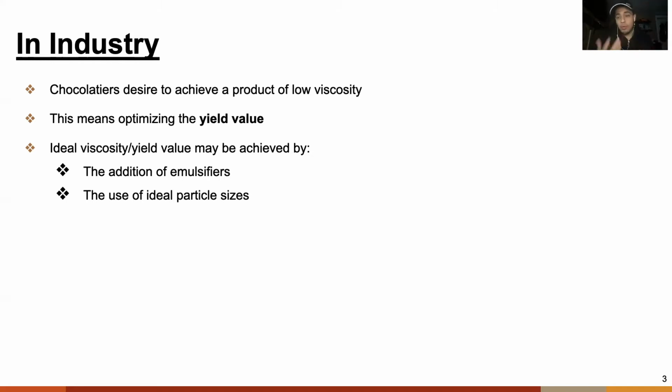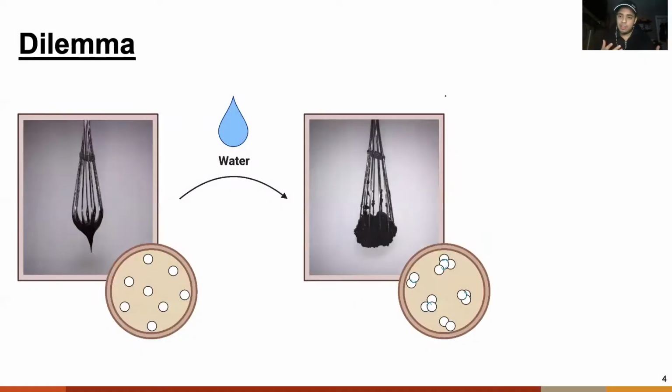And so before that, chocolate might have been solid, the soy lecithin essentially had that function to facilitate the flow. But another way we can go about this is altering the size of particles we have in our chocolate. Specifically, we can look at altering the sugar particle sizes. If you have these larger particles, there's less interactions going on, there's less contact points. However, you'll have a much grittier chocolate. And so you can supplement this by having smaller particles, which act as spacers between the larger ones, so that everything flows better, and it eliminates that grittiness that would be offered by just using a single larger particle size.